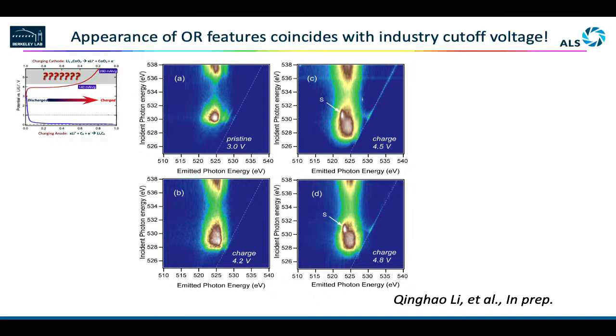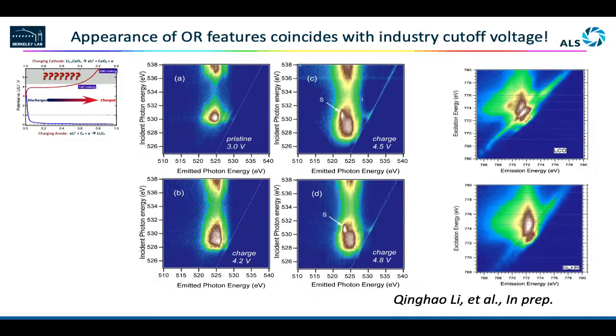And then we did very careful in situ cell work with a thin film company, and Jinhua has developed all kinds of in situ cells of this material, and also ex situ experiments of both the oxygen and the cobalt L-edge RIXS. Coupled with theory, we're trying to get something. So here I just want to show one very interesting finding. So that is the lithium cobalt oxide so far.